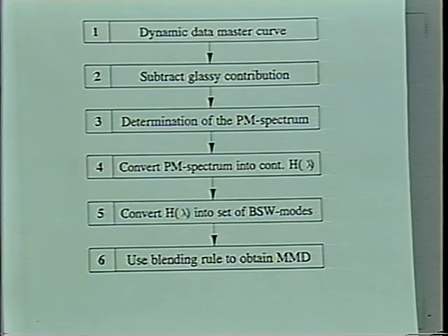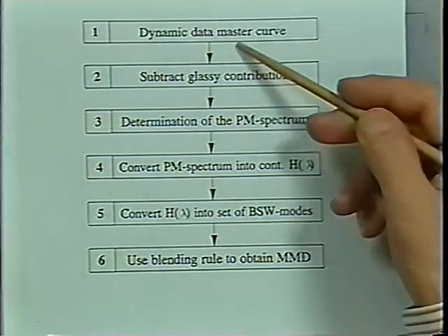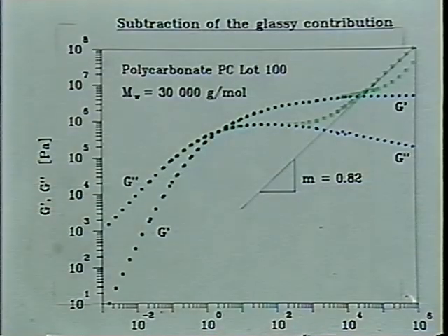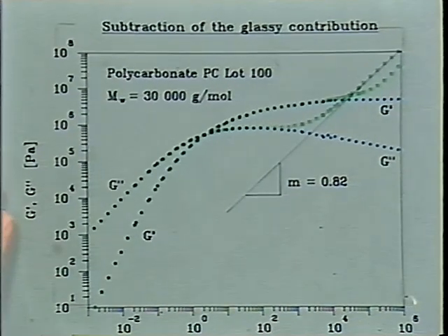And we can only do that because we now know the relaxation spectrum of the monodispersed polymer. If we did not know the monodispersed relaxation, then all of this would be hopeless. But since we know the monodispersed, we can do that. If you know the results, it works very well. I'm not sure whether it works if somebody gives you a polymer with its GPC, and you do the calculation, and whether everything is agreeable. But for polycarbonate, for instance, we got this from GE, typical commercial polycarbonate.